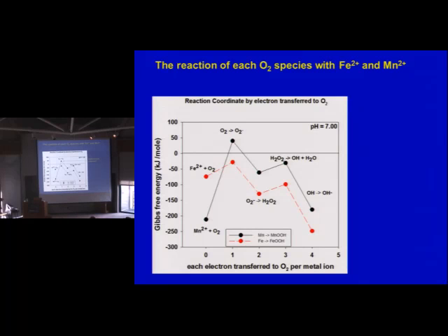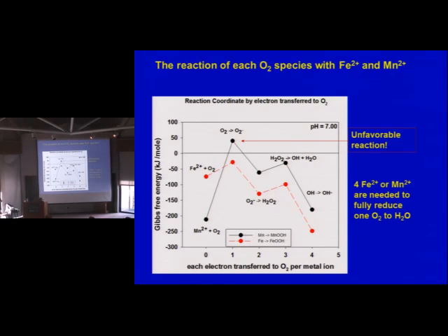Notice, though, that every one of the other reactions that occurs, one at a time, with manganese 2 or iron 2, would be favorable. All right? To get one oxygen to go to one water, you need 4 iron 2s going to iron 3, or 4 manganese 2 going to manganese 3, if you will. And if you look at this little step right here for the iron, you would say, okay, this went up a little bit, but that's an energy of activation which could be easily overcome. All right? And that's just a simple way of looking at that. But this gives you a good reason why manganese 2 is not oxidizing.